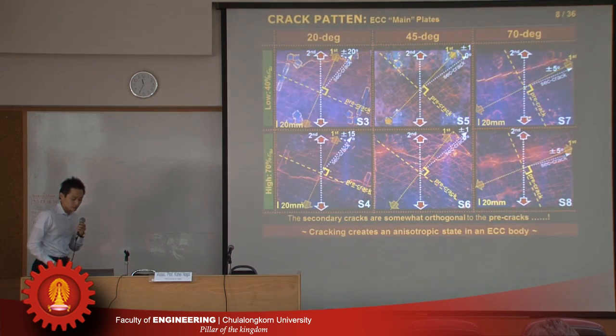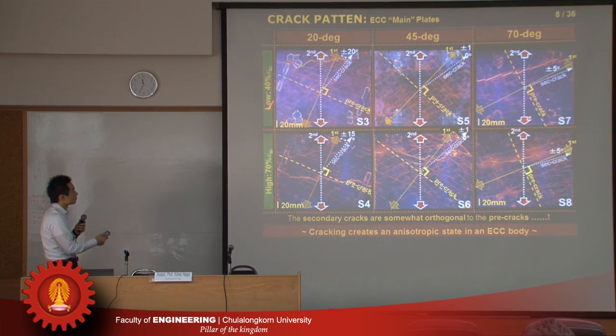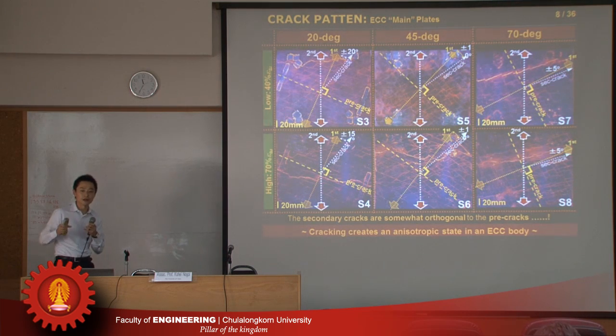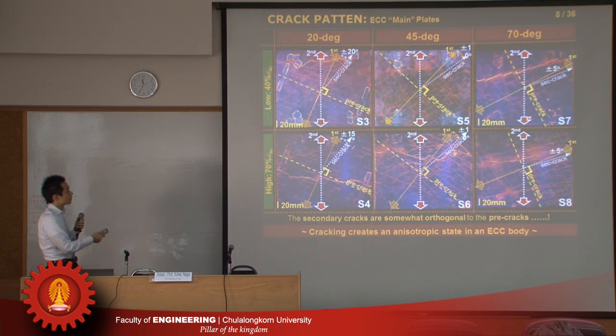So this is a result of the cracking pattern after the secondary loading. Actually, we give two types of loading level, 40% or 70%, but it doesn't matter so much. Anyway, the 20 degrees, 45 degrees, 70 degrees. So the yellow line is the pre-crack, meaning the initial loading, and this dotted yellow line shows the initial cracking direction, and the red one is the secondary principal direction, meaning first damage and second loading.